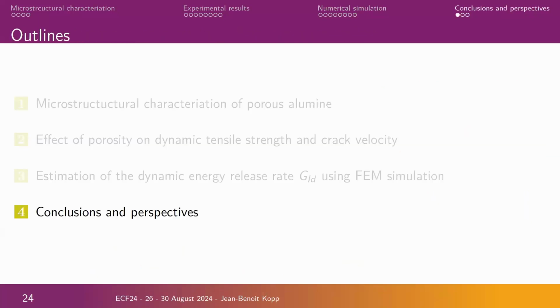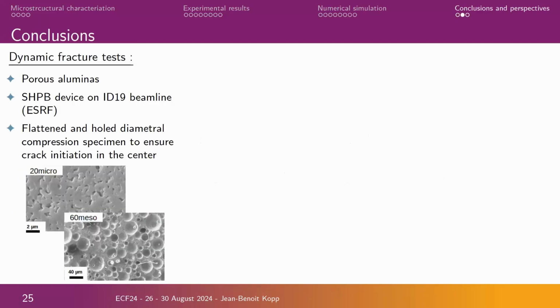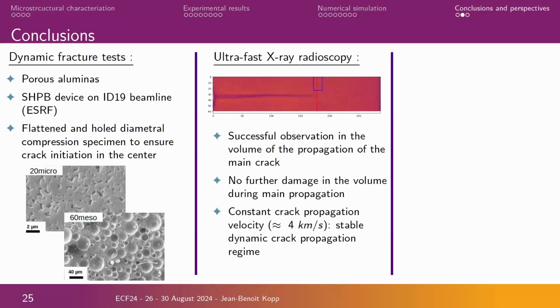So to conclude on this presentation, so first of all, we have made some dynamic fracture tests using a very special instrument in the ESRF on the ID19 beamline. It was possible to study the influence of the porosity rate on the fracture properties. We were able to follow a dynamic propagation at a few kilometers per second.